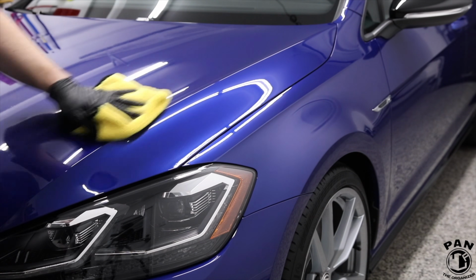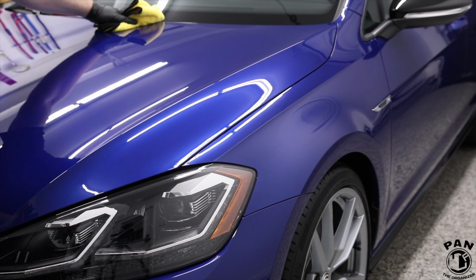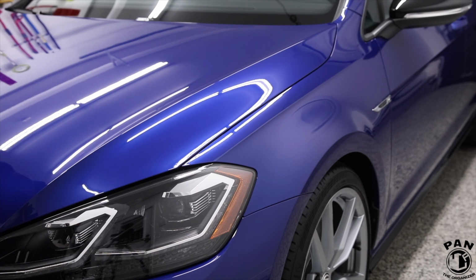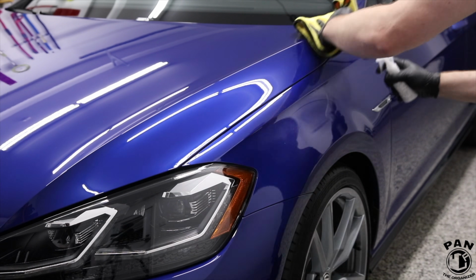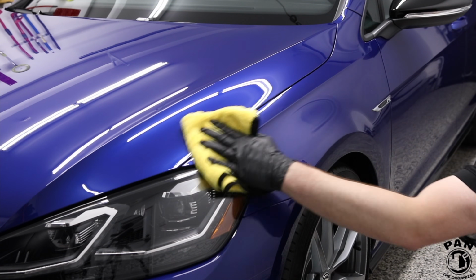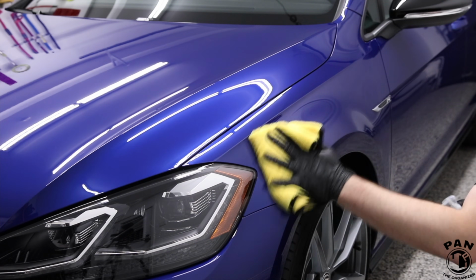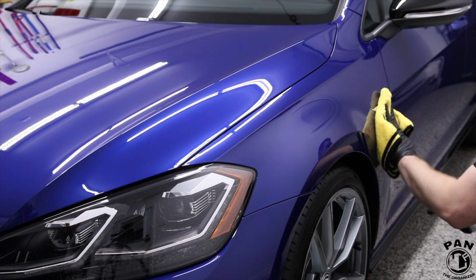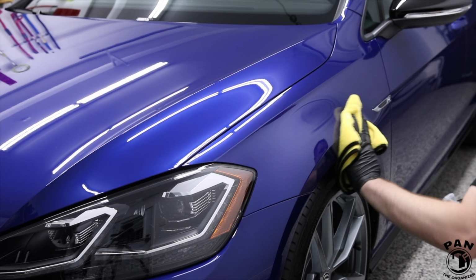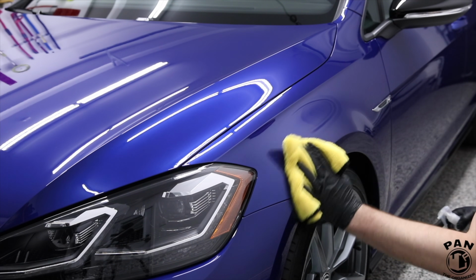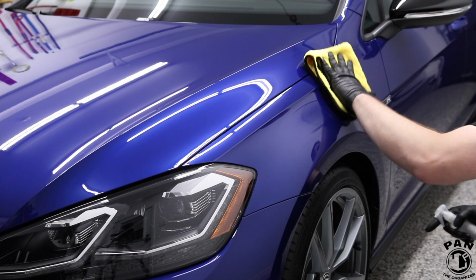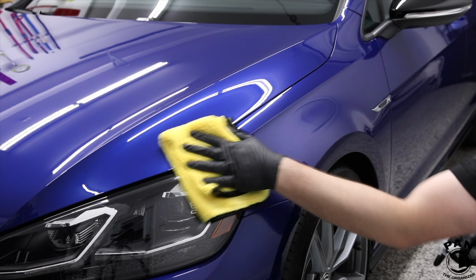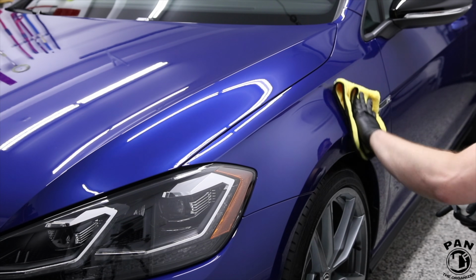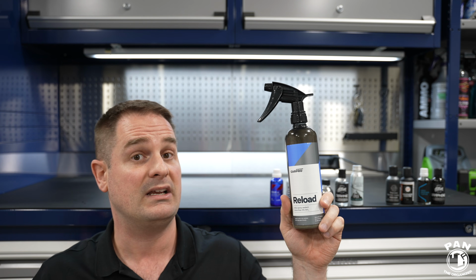So it's not so much for durability, but more to help protect the coating itself for at least the first couple of weeks while the coating is curing. Because although most coatings require 24 hours of not being exposed to water or rain after application, that is crucial, well, after that first day you're going to drive in the elements and it might start to rain, or you get some snow, or who knows what is out there. These are going to help protect the coating against that, because coatings typically need 7 to 14 days to reach full hardness and the full curing time, right?